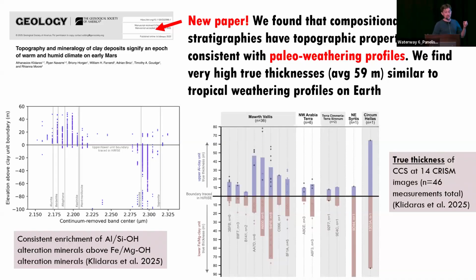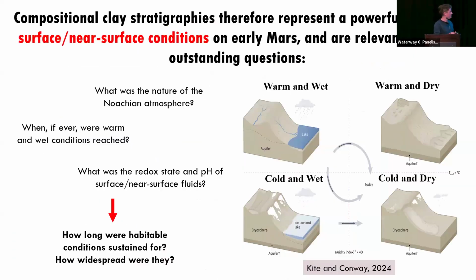And what we are doing is using their topographic properties to test competing hypotheses about how they form. So we actually found their topographic properties favor a subaerial weathering formation origin. And we measured their true thickness, taking into account the strike and dip at loads of places on Mars. And we found really high values, but those are still similar to tropical weathering profiles on Earth. And why care about these?